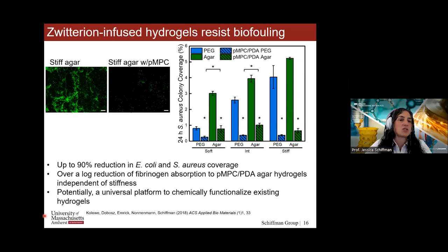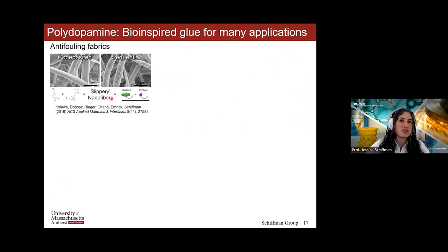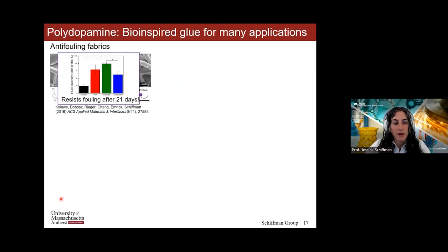This is super cool. Okay, so what else have we done with polydopamine glue? So we love our textiles. We had electrospun these cellulose nanofiber mats. And then we showed these as a kind of membrane treatment that we could soak in a protein solution for 3 weeks. And here, the transport through those materials is the best, is retained, when they are coated with our polydopamine glue. On this particular plot, we actually want a higher flux recovery ratio, meaning we retain the same property.